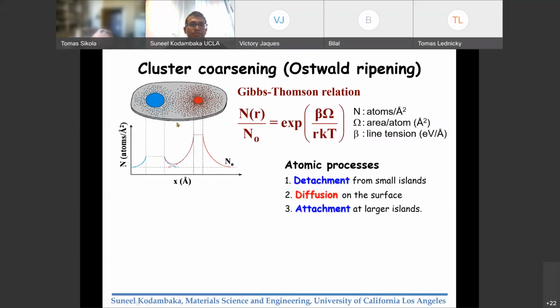And for this small cluster to disappear and for this large cluster to grow, one can envision 3 different processes that have to happen. One is that the atoms from the small cluster have to detach. They have to either diffuse on the surface or desorb and come back from the vacuum, and then reattach at the larger cluster. And so one can identify which is the rate limiting mechanism in each of these 3 processes,